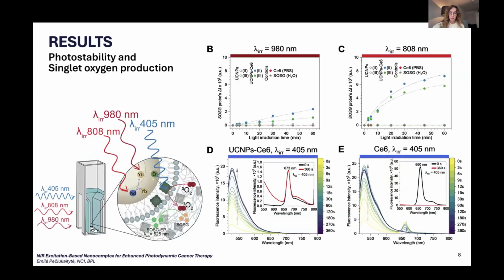So while spectral analysis confirmed complex formation and energy transfers, the production of singlet oxygen upon near-infrared light irradiation indicates whether the system has therapeutic potential and is actually working. By using 808 nanometer and 980 nanometer lasers to excite upconverting nanoparticles, and a 405 nanometer laser for direct chlorin excitation, we found that both nanocomplexes generated singlet oxygen efficiently under near-infrared light irradiation, whereas neither UCNPs alone nor chlorin e6 alone produced detectable singlet oxygen.